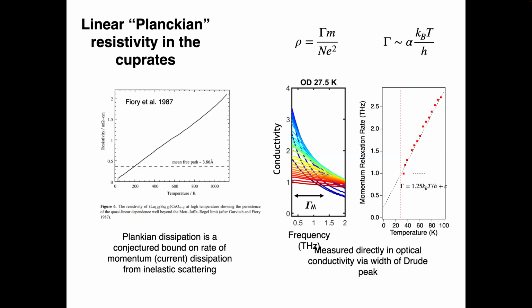When you look at data like this, the inference is that you're looking at the temperature dependence of a scattering rate. But when you measure the resistivity, there are some assumptions that go into that. When you measure the optical conductivity, you can just see it directly, right? So this is the optical conductivity measured with terahertz as a function of frequency. You have these curves which have particular widths. And this is not a level of interpretation. It's just from the definition of the conductivity itself. The width of this curve is the rate that current dissipates in the system.